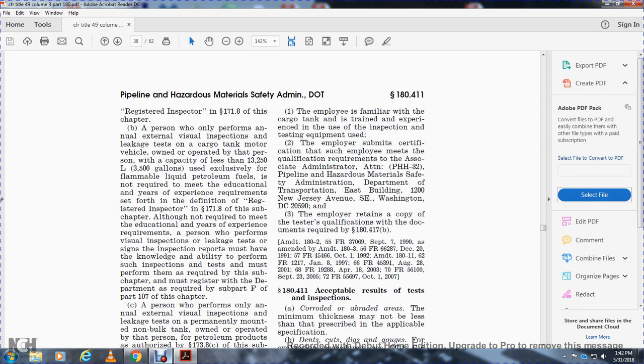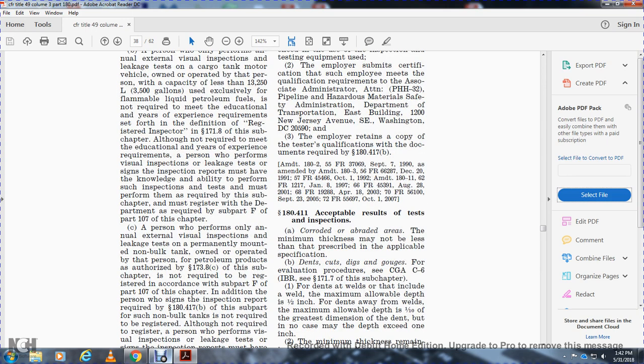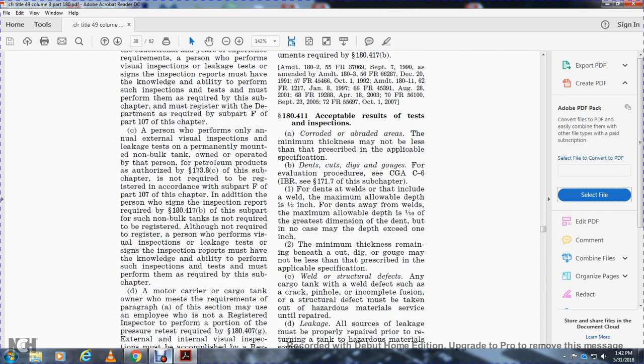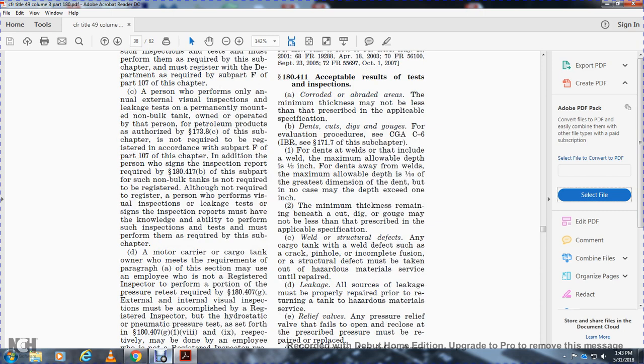180.411: Acceptable results of the test and inspection. Corroded or abraded areas with the minimum thickness may not be left less than the prescribed applicable specification. Dents, cuts, digs, and gouges are evaluated as prescribed in CGA C-6. For dents that include a weld, the maximum allowable dent is 1/2 inch. For dents not at welds, the maximum allowable depth is 1/10 of the greatest dimension of the dent, and in no case may the depth exceed 1 inch. Minimum thickness remaining beneath cuts, digs, and gouges may not be less than prescribed in the applicable specification. Weld defects on the cargo tank, such as cracks, pinholes, or incomplete fusion, are structural defects and must be taken out of hazardous material service until repaired.